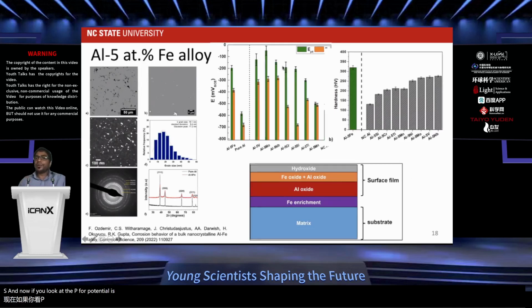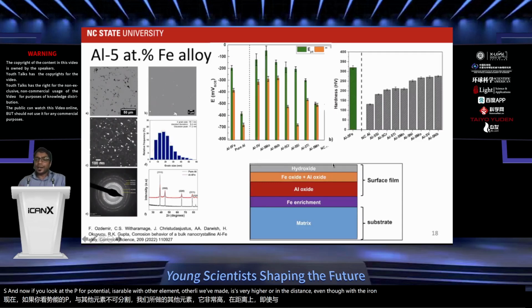Huge amount of iron present in aluminum. We did the ball mill and we got good solid solubility of iron and a pretty unique microstructure. Iron was very well distributed in the matrix. And now if you look at the pitting potential, it is comparable with other alloys we made. It's very high corrosion resistance, even with the iron, and high hardness.